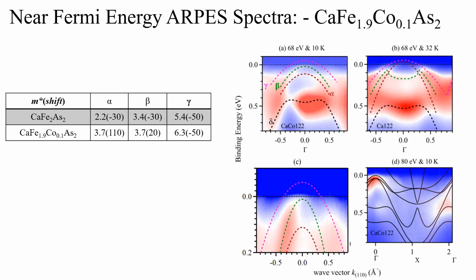Sorry to interrupt. I have a small question. Yeah, ask. Since your sample is superconducting, there will be one superconducting energy gap, and also due to some antiferromagnetic ordering, some other gaps are open. Yeah, but in this case, there is no antiferromagnetic ordering. The cobalt concentration that I chose leads to the complete suppression of the antiferromagnetic ordering. So in this compound, we don't have any antiferromagnetic ordering.